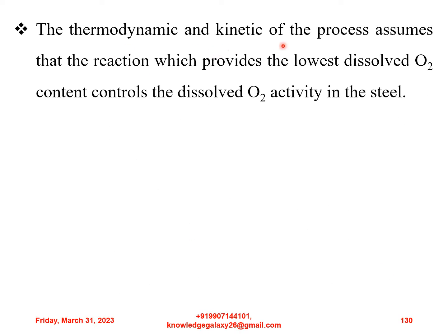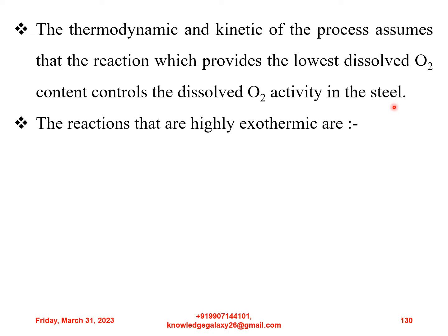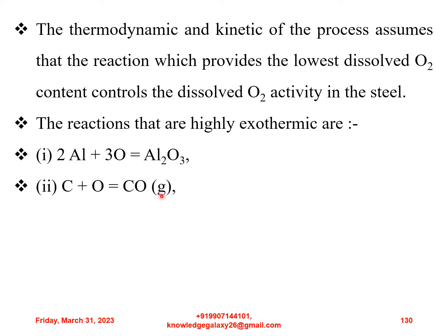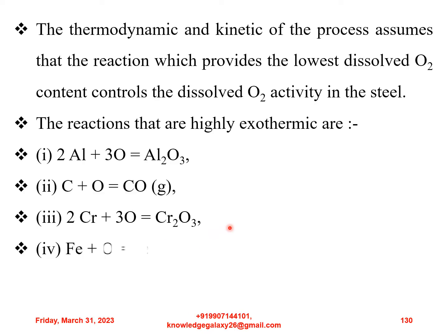The thermodynamics and kinetics of the process assume that the reaction which provides the lowest dissolved oxygen content controls the dissolved oxygen activity in the steel. The reactions that are highly exothermic are: first, 2Al plus 3O gives Al2O3. Next is C plus O, this gives CO. Third one is 2Cr plus 3O, this gives Cr2O3. Next is Fe plus O, this gives FeO. And Si plus 2O, this gives SiO2. All these reactions are exothermic in nature, as I have described earlier.